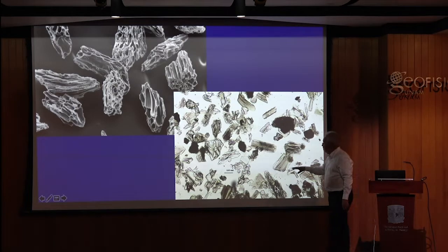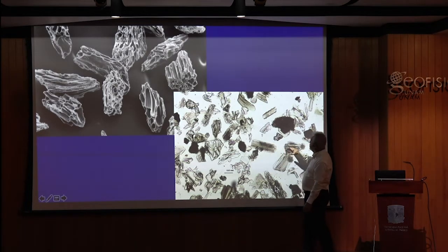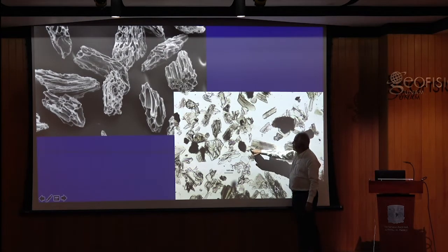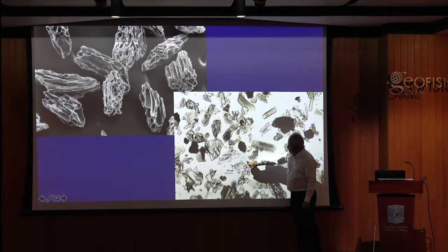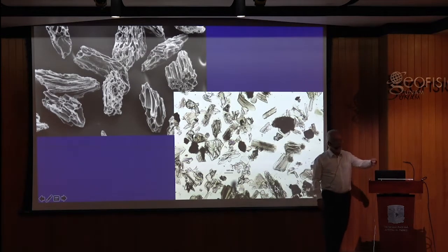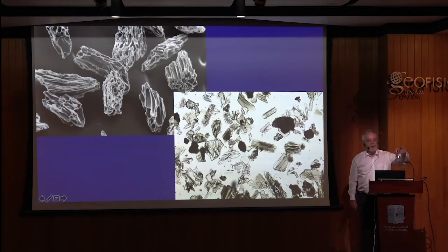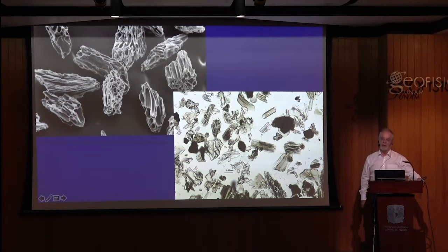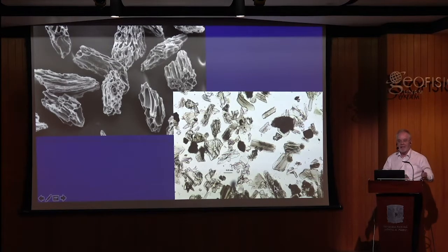So the idea was that next to the beautiful crystals that you see here, and the opaque phases here are probably crystals, you also have these beautiful broken pieces of glass, which you would also see if you dropped this on the floor and looked at the broken glass particles in the same size range. Can it be that simple?